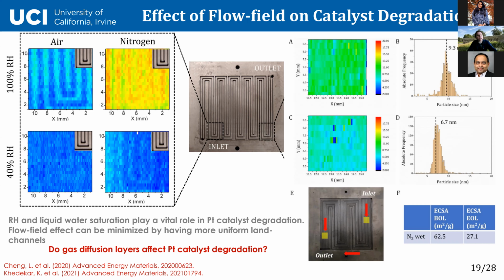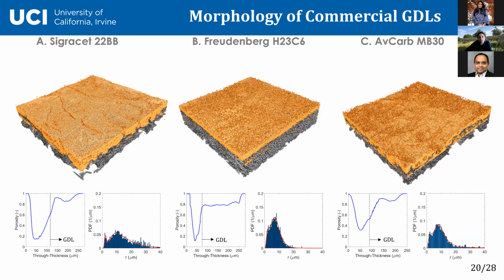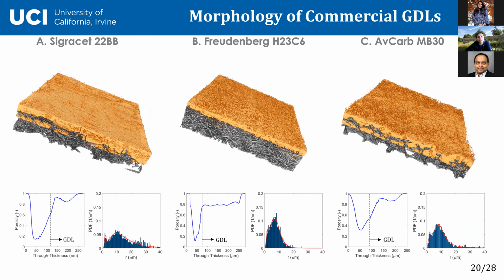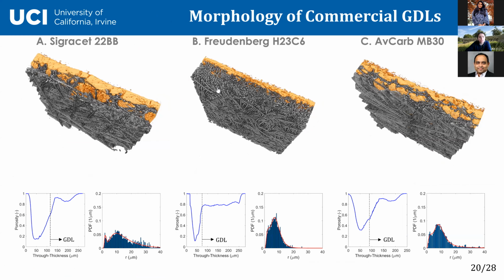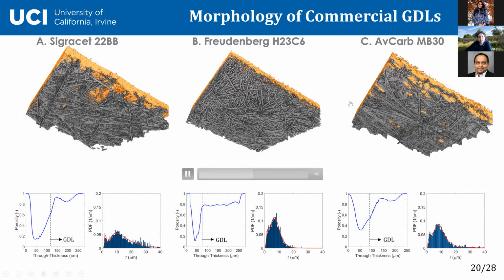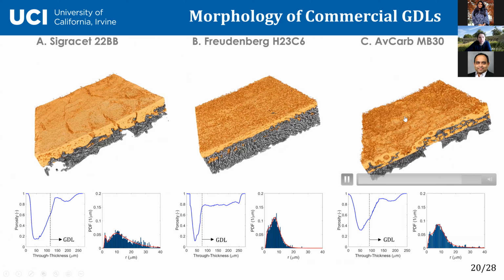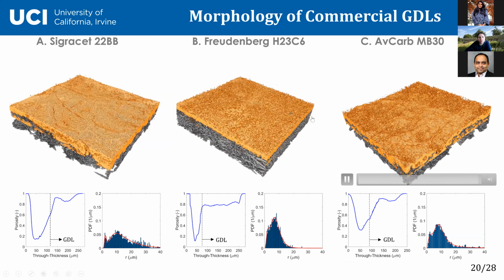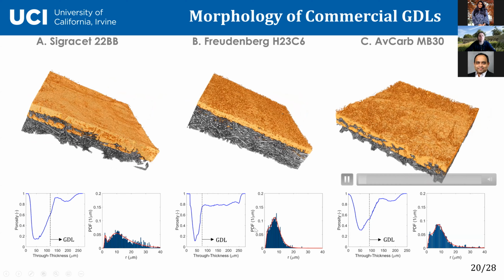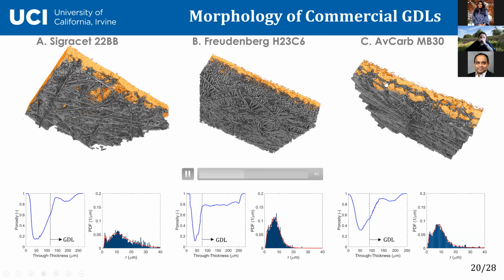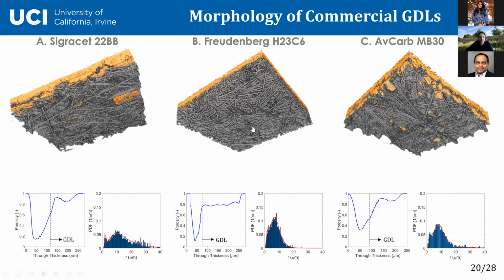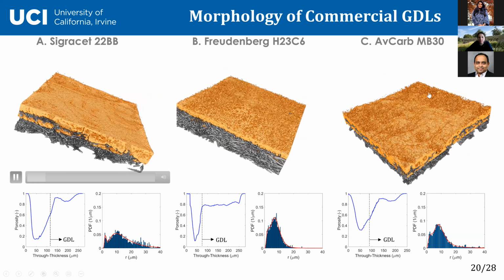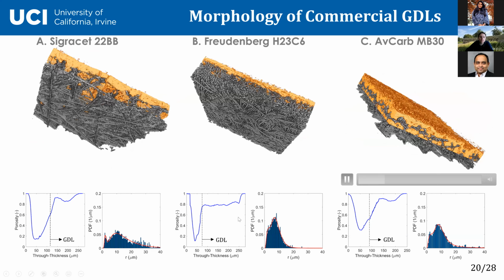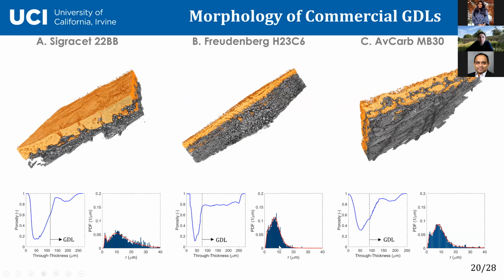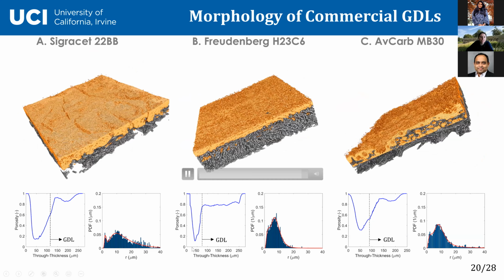Next question we had: how do gas diffusion layers impact platinum degradation? So these are inert layers. They're made out of carbon, and they have a fine microporous layer, which is shown here in orange. So we picked three from commercial suppliers, and they are very different. These are the three most used in the industry currently, right? You have SGL, you have Freudenberg, you have AvCarb. You can see one has a cracked microporous layer, one has a very uniform microporous layer, one has a really embedded microporous layer. You can see pore size distributions, porosity, all from tomography, all of them very different, right? And thickness is the same.